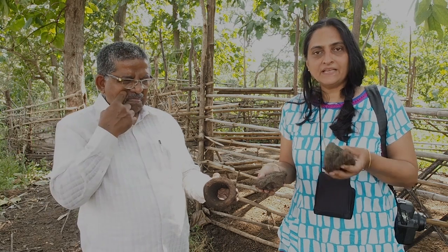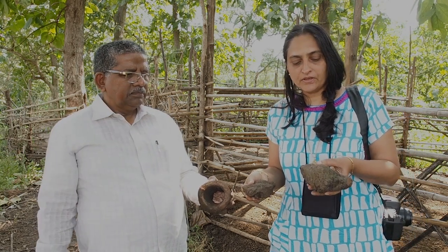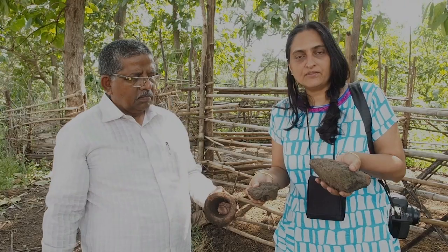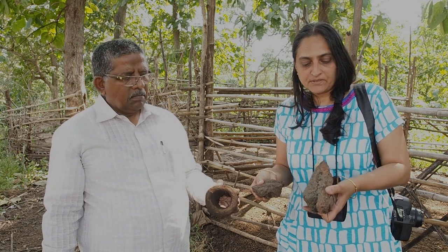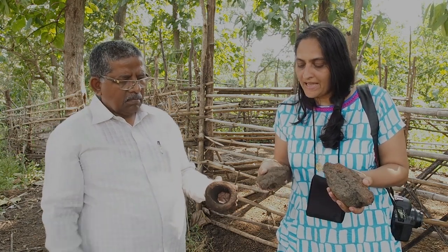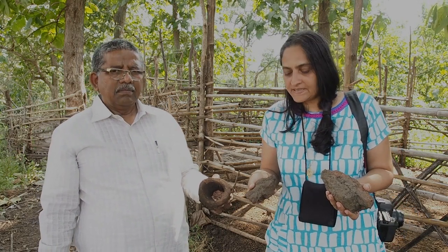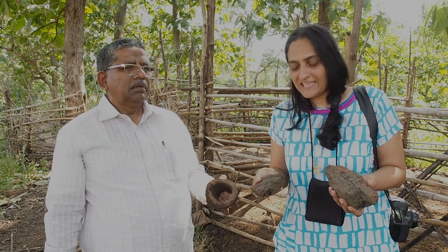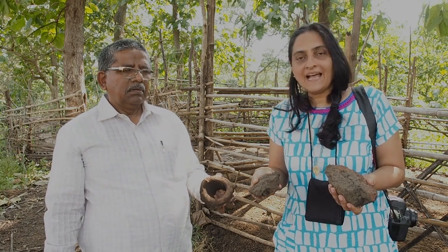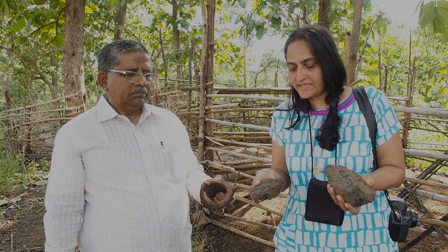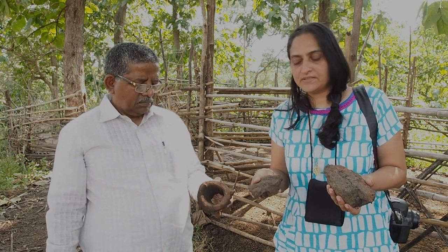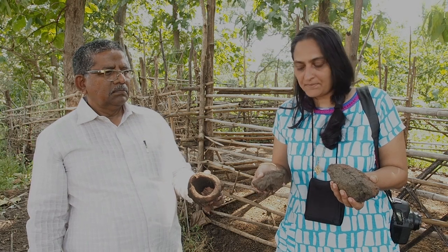And what you're looking at here is a portion of the furnace walls, the lining of the furnace, which is made of brick and other refractory material. These are various portions of the furnace walls which are broken here. And this is what we call slag in archaeometallurgical terms. Slag is the waste which forms as a sort of liquid on top of the bloomery iron, and that collects all the impurities, such as the quartz impurities and so on in the iron ore, any other gangue and siliceous matter. The iron bloom is below and the tap slag flows on top.